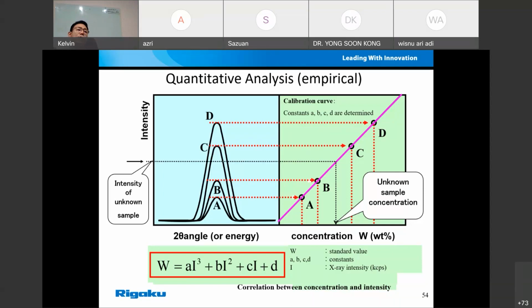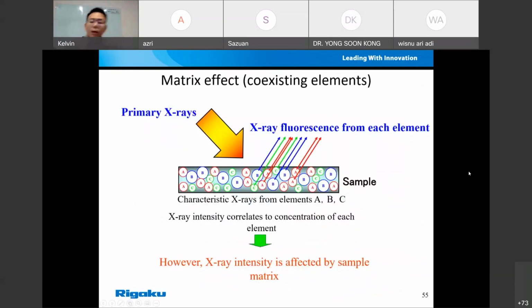So the second way of doing it is by having a secondary standard, where you send your sample to ICP, and from there we can generate the standard for calibrating the system. So put it this way, XRF analysis is good when you want to do quantitative analysis. The empirical calibration method gives you the most accurate result, and how accurate the calibration is depends on your standard. And of course, there are a lot of effects contributing to the error.